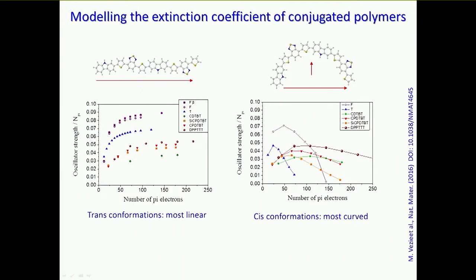And so we needed to consider both of these extremes. And when we did that, we saw that something rather interesting was happening in the case of the all-cis configuration. In the cis configuration, the polymer is going to be as bent as it possibly can, and it's going to become more bent as the chain becomes longer. What we were seeing was that the specific oscillator strength rises, and then it turns over, and it turns over at a different place for the different chemical structures. That's all got to do with the geometry of the individual monomer.